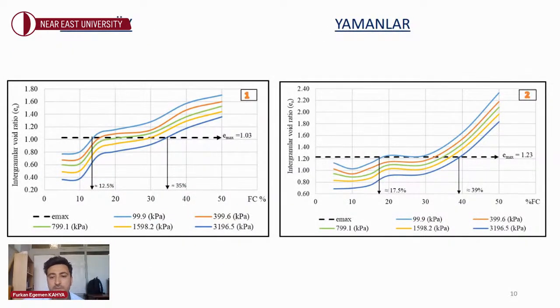Also, from a different perspective, if the fine content that shifts the soil behavior from the granular part of the soil to the fine part of the soil is considered as a function of effective stress, it defines the transition fine content zone. Starting from this point, Nazarköy samples show a transition zone from 12.5% to 35% mica content. As for Yamanlar samples, they show a transition zone from 17.5% to 39% mica content. Also, initial values of 12.5% and 17.5% mica support the threshold content in the graph on the previous slide.